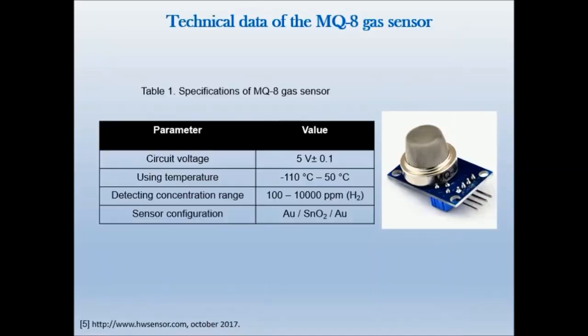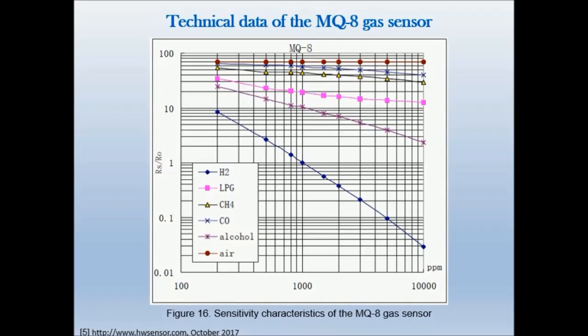Now, regarding the technical data of the MQ8 gas sensor, here are the specs of it. It operates with a circuit voltage of around 5 volts. The using temperature is in the minus 110 Celsius to 50 Celsius, and the hydrogen concentration range that could be detected goes from 100 to 10,000 parts per million. This sensor is made of tin oxide and it contains also gold electrodes. Regarding the sensitivity, although it can operate with other gases such as LPG, methane, carbon monoxide, or alcohol, the best sensitivity values are for hydrogen.